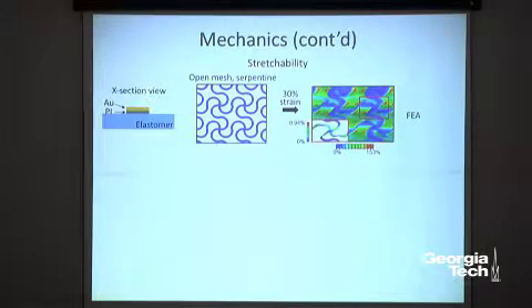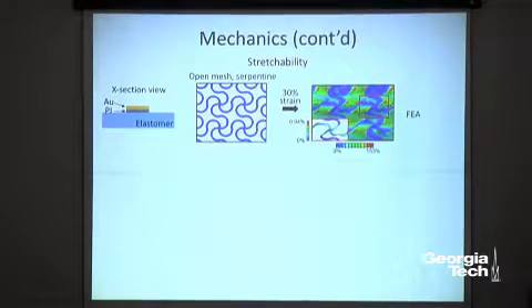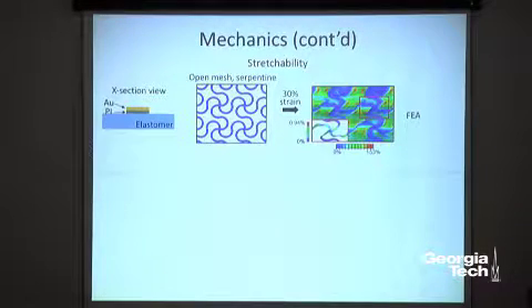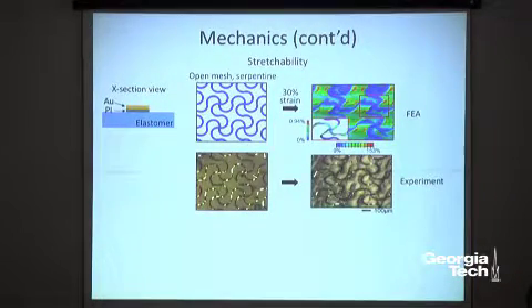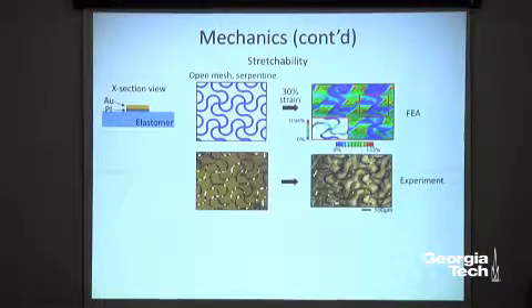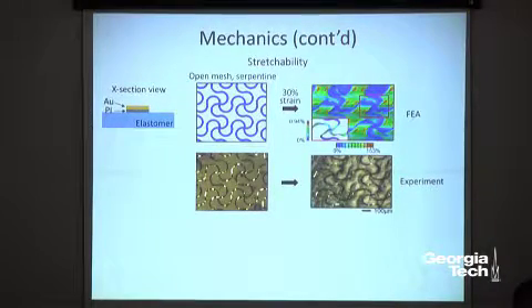You can simply utilize a new pattern when you design your electrode or system. So instead of using linear straight lines to design electrodes or electronics, we came up with these open mesh serpentine-like structures. Right? So basically we give room to be stretched, while it's also flexible based on the thickness. So based on this finite element modeling, you can imagine how much stress can be applied and whether this material is fractured or not. So here in this case, we have this gold membrane, 200 nanometers in thickness. And with 30% strain, it's not going to be fractured and is stretchable as shown over here.